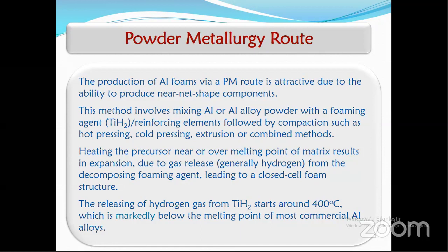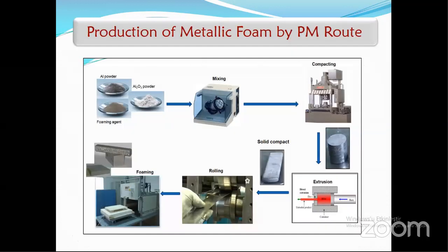The release of hydrogen gas from titanium hydride starts around 400 degrees, which is markedly below the melting point of most commercial aluminum alloys. This picture shows the production of metallic foam by the powder metallurgy route. Aluminum powder, foaming agent, and some reinforcing elements such as alumina. We are mixing them, generally using a three-dimensional turbulent mixer, and then compacting to get green dense materials. Since it contains lots of porosity and cracks, it is impossible to form them. That's why we are hot extruding that material to obtain a solid compact, and then rolling, and then foaming in a special furnace to get the metallic foam.